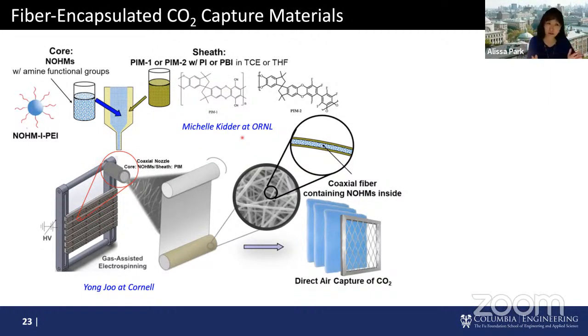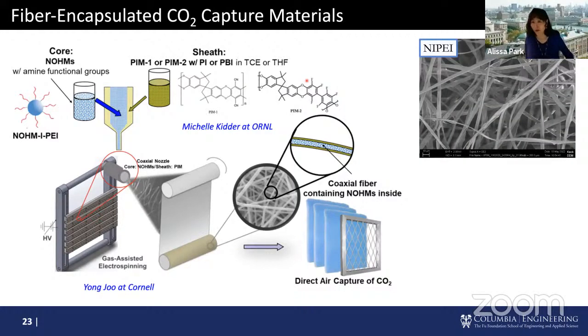highly porous, but I had one more request. Can you make it hydrophobic? So hard material called PIM1, PIM2, these are very porous, but at the same time has these fluorine groups making them hydrophobic. So what we hypothesized was that we might be able to selectively reject the water while letting CO2 in to capture CO2 within these fiber systems. Here are some of the SEM images of our fibers we actually made with the NOHMs inside.